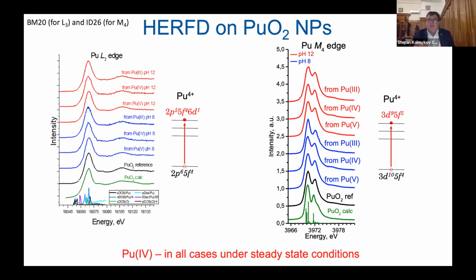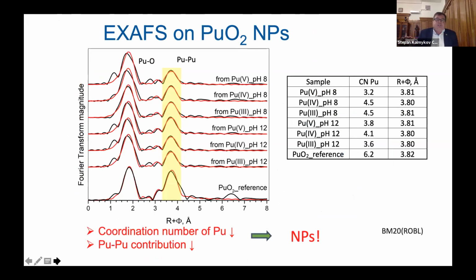So what we found here is that there's only plutonium-4, so we don't see any traces of plutonium-3 or plutonium-5 in these nanoparticles. The EXAFS was done to characterize the local molecular environment, and you can see here that the coordination number of plutonium is decreased, because for 2 nanometer sized particles the number of atoms on the surface starts to be important, and the coordination number for the surface plutonium is different compared with the bulk plutonium. That's why we have the decrease in coordination numbers, and the plutonium-plutonium contribution is also lower compared with the microcrystalline